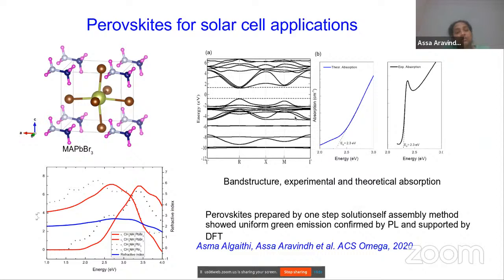And then we used DFT to calculate the band gap, and we also calculated the theoretical absorption, which was matching with the experimental data. And we successfully explained phenomena like the charge transfer and band structure. Also, the dielectric properties were calculated, which were also very much in agreement with the experiments.